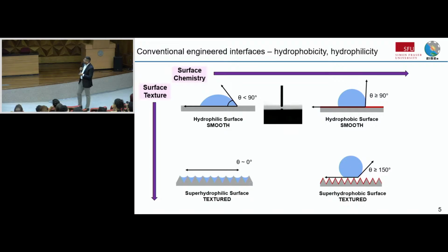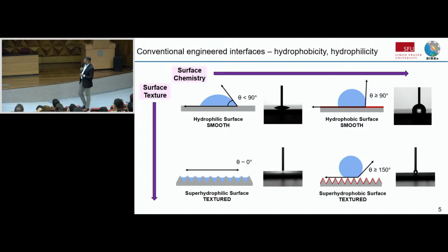So the way we surface scientists do this is contact angle measurements. So again, a hydrophilic surface, contact angle is less than 90. But now if you texture it, it becomes extremely super hydrophilic. That means the contact angle, as you can see in that video, is 0. A hydrophobic surface is 90 degrees, but then if you add texture, you make it extra hydrophobic. So that means now you have this contact angle that's greater than 150. The droplet doesn't want to interact with the surface.